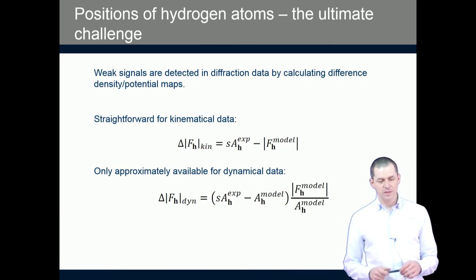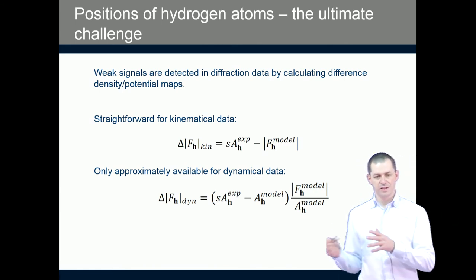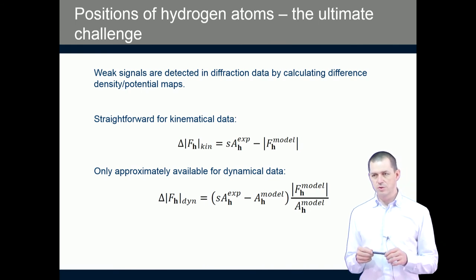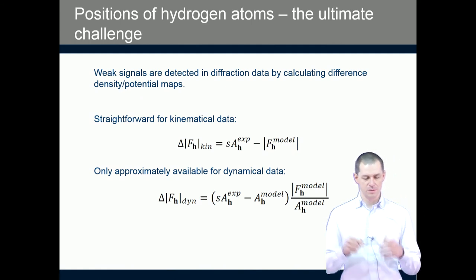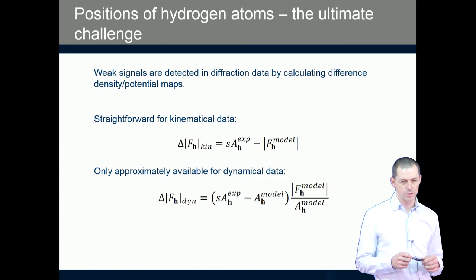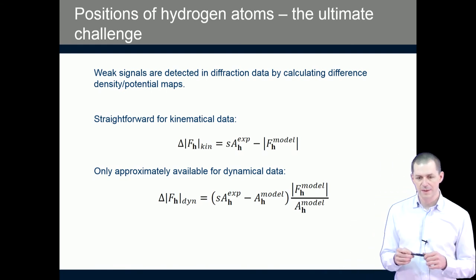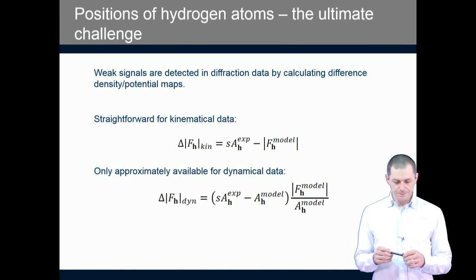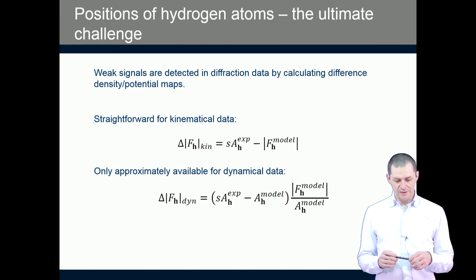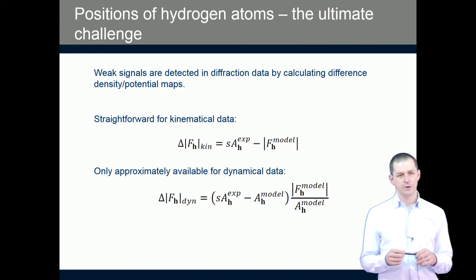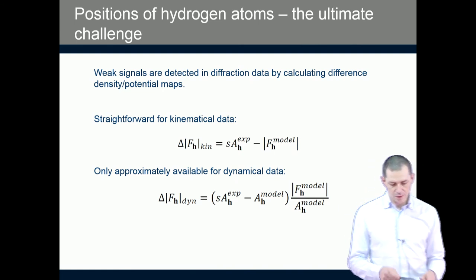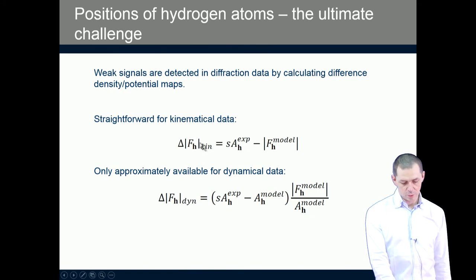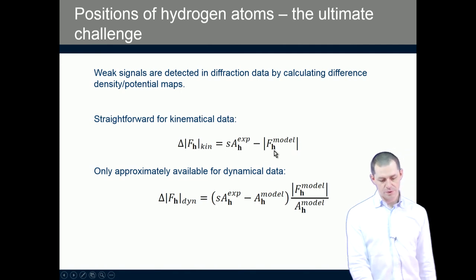So the weak signals in diffraction are detected during structure solution using the difference Fourier map. You have done this many times in the practicals, so this is a routine procedure during the structure solution process. For dynamical diffraction, the calculation of difference Fourier map is not as straightforward as for kinematical data. For kinematical data, you just calculate a difference of the structure factor amplitude, so this would be the experimental one, properly scaled, and this is the model structure amplitude.